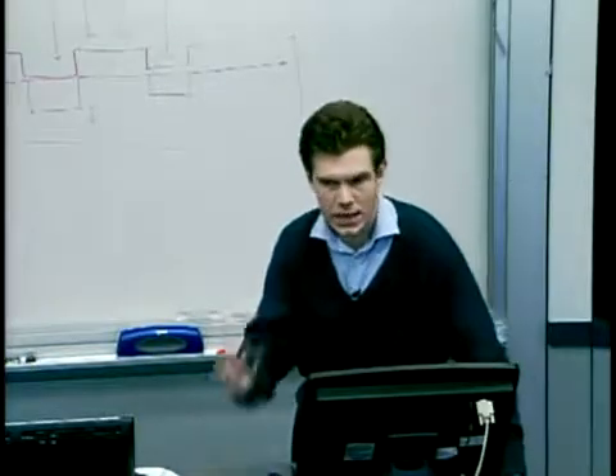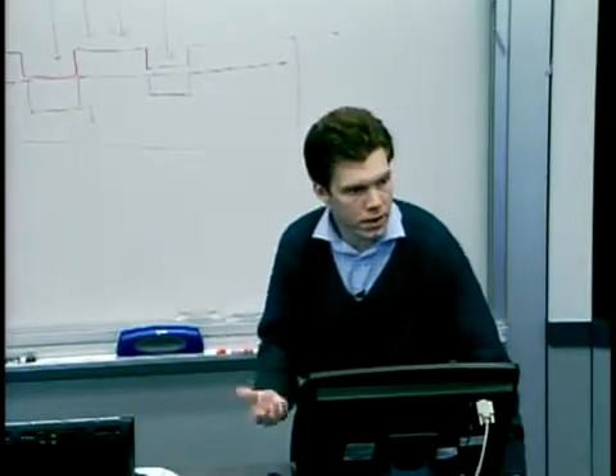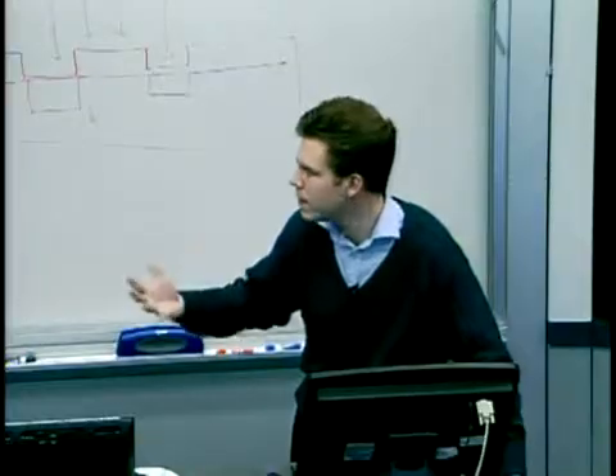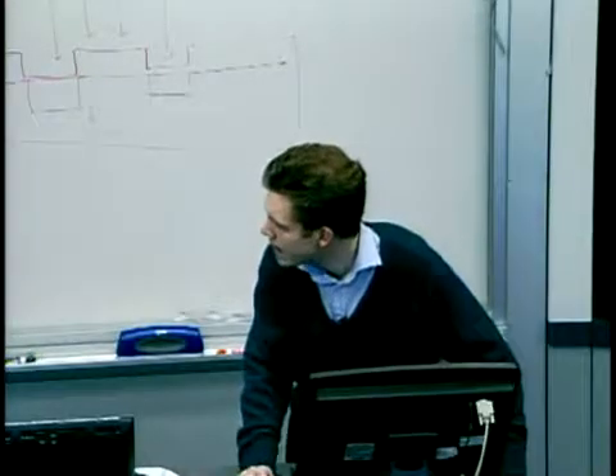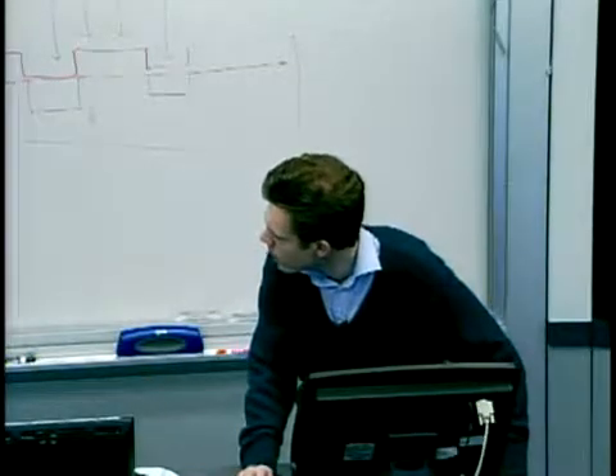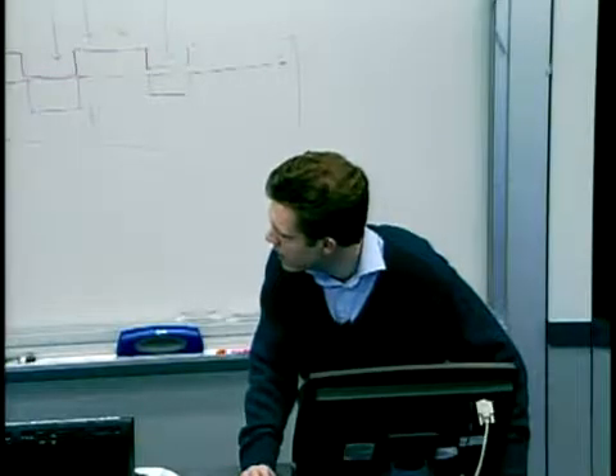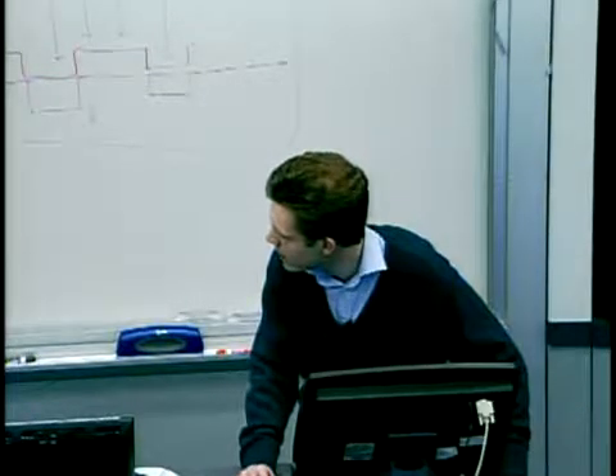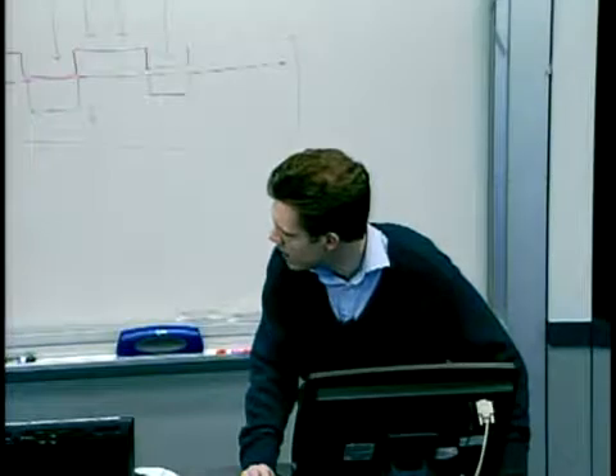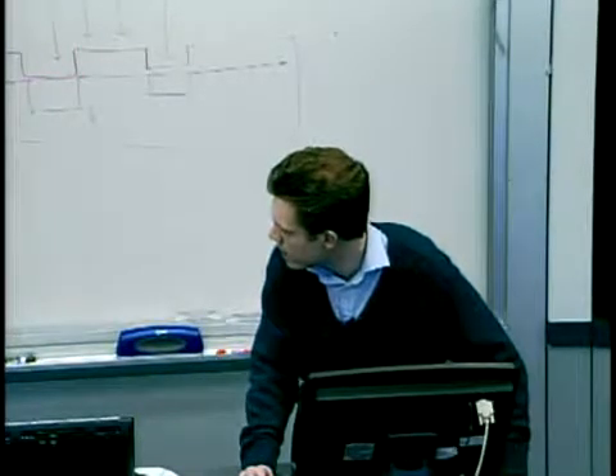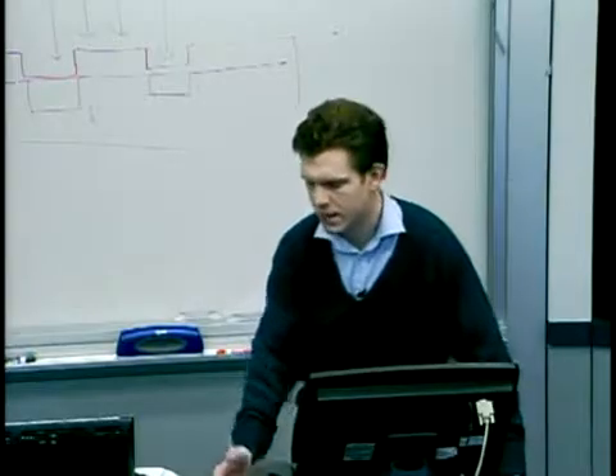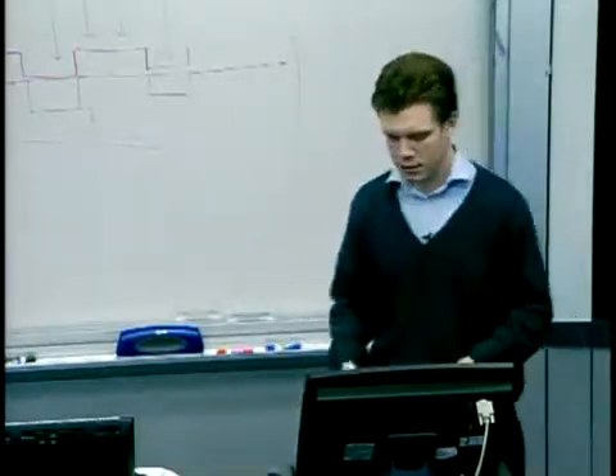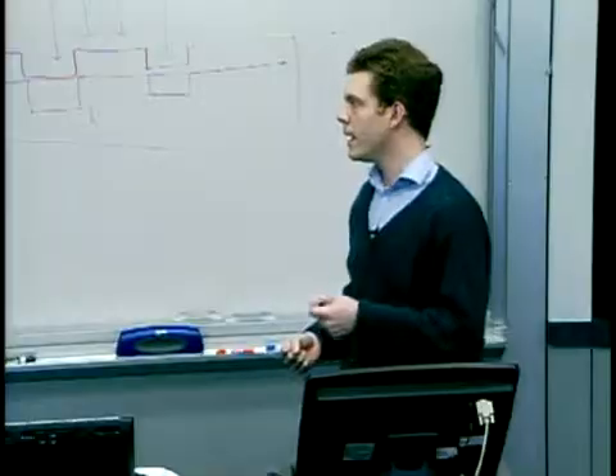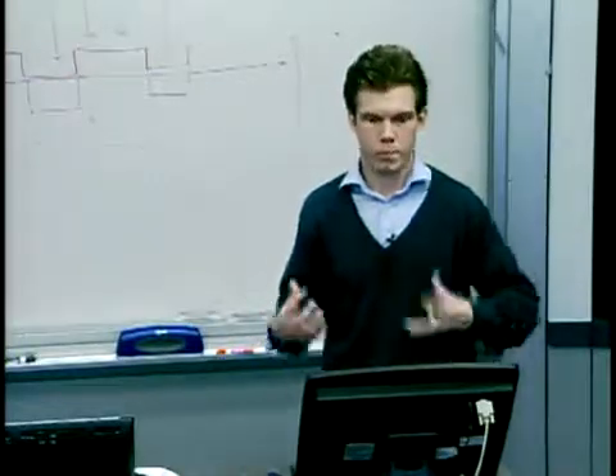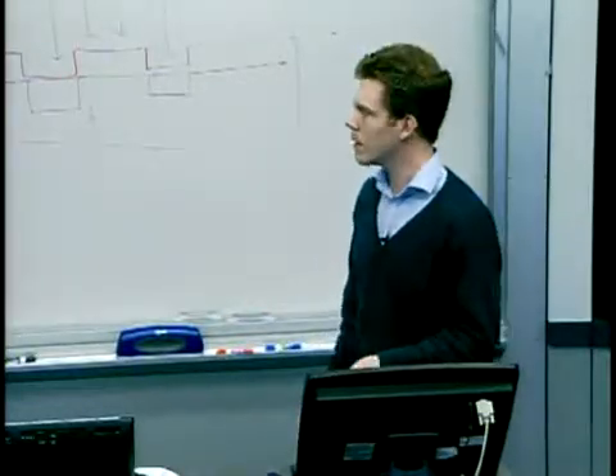We did that using an interferometer, scanning from above, measuring the topography, and so we were able to see various things, that the embossed depth was higher on this side than on this side, that near the edge of the wafer the embossed features tailed off in height. And so these are the sorts of things that we need to come up with ways of predicting so that we can counteract them.